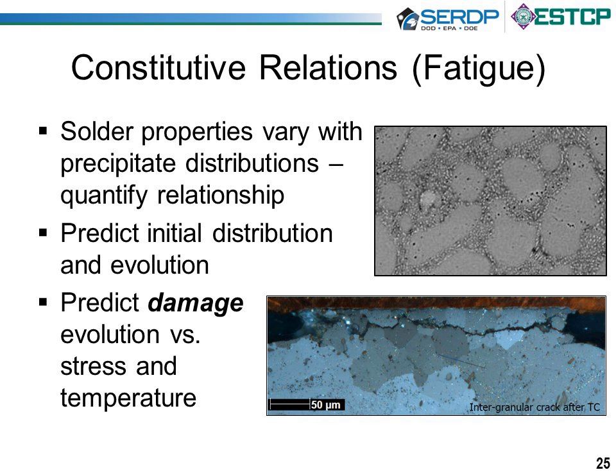There are two aspects to it. One is that the properties actually depend on the orientations of the tin grains, but that's a randomizing factor, so that simply gives you some variability to your results, and you can look at averages or the worst case or whatever. But the other thing, which is really the more disturbing, is that something is changing as we go. That's something we're not used to from modeling, so we have to count on the fact that the properties of the material are not the same in the first cycle as in the next one and the next one and so on, or the same after a few weeks of sitting around. And that's determined by the fact that the solder joint is a precipitate hardened material.